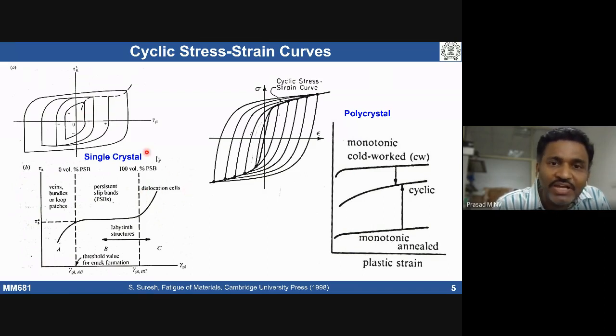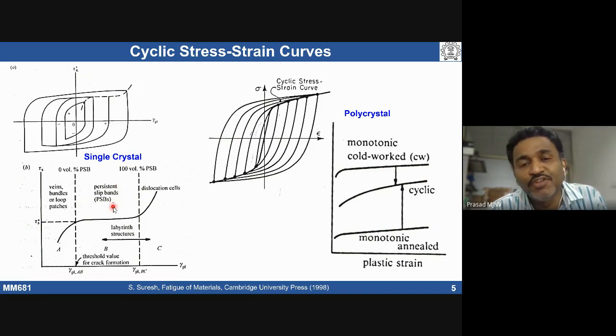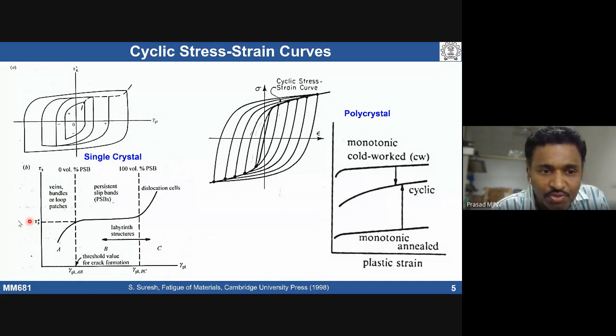Typically, if we deform a material, be it single crystal or polycrystal, one of the characteristic features of the microstructure evolution is formation of persistent slip bands. In single crystals, apart from persistent slip bands, we see veins and bundles, kind of loops. In polycrystals, we directly see persistent bands, and we may not see veins and bundles. So a labyrinth structure can develop, a combination of persistent slip bands plus dislocation cells, which we call labyrinth structures. This can form in both single crystals as well as polycrystals.